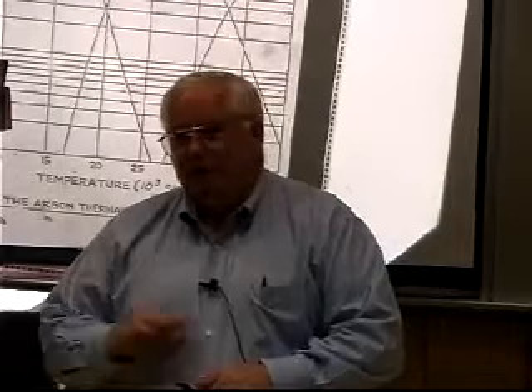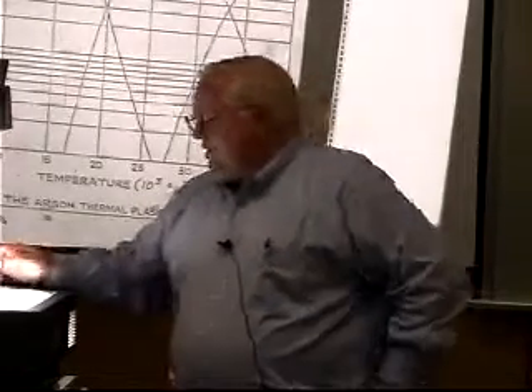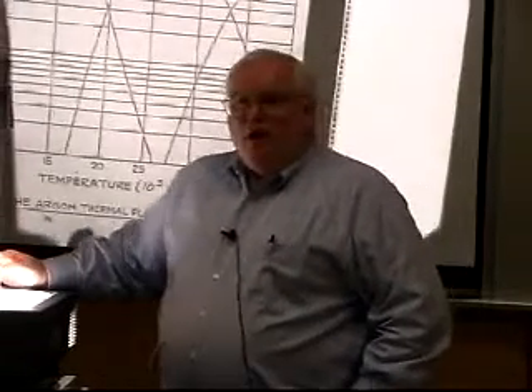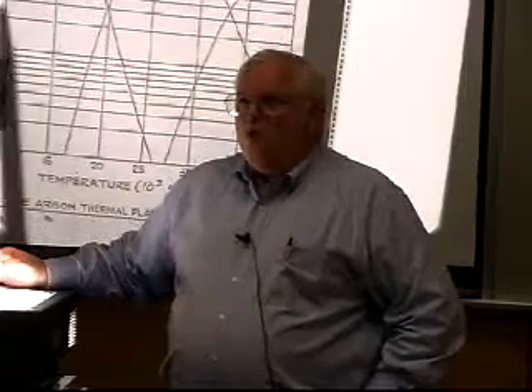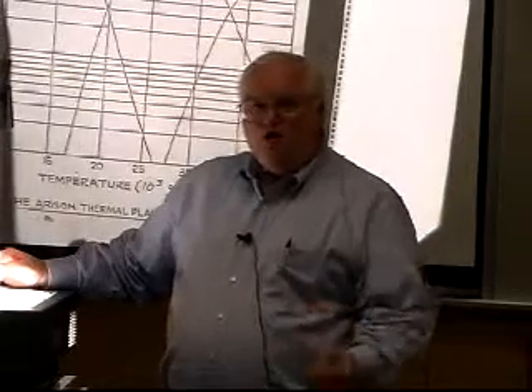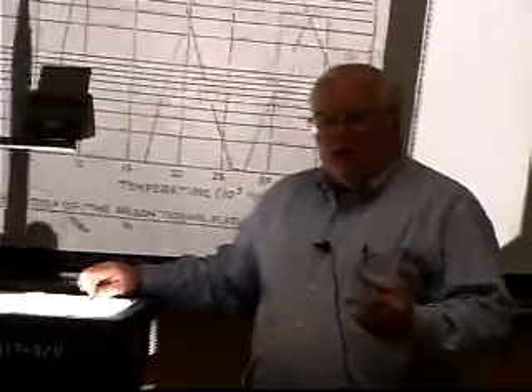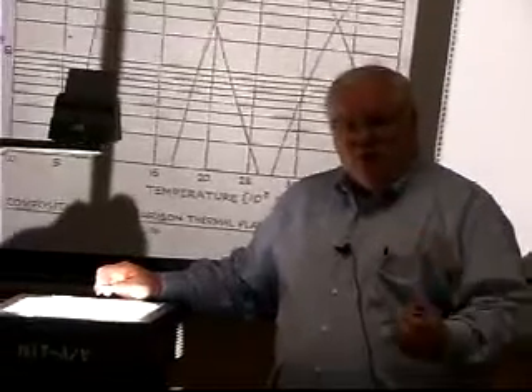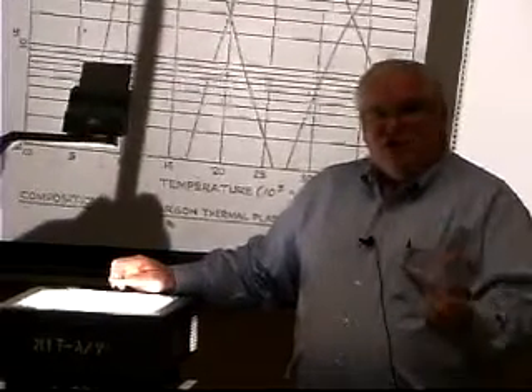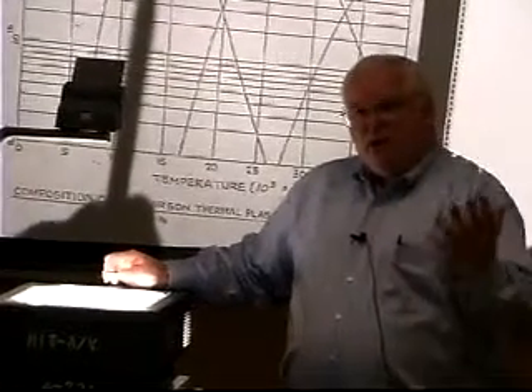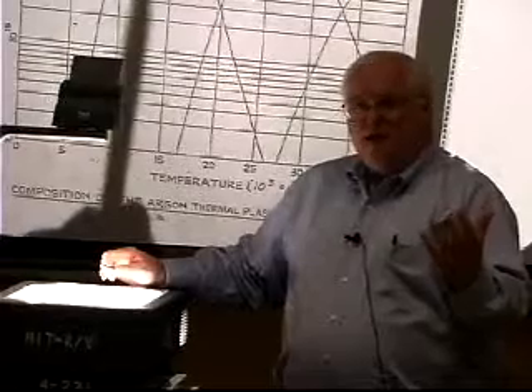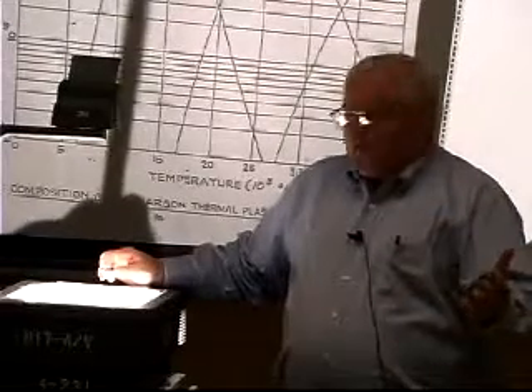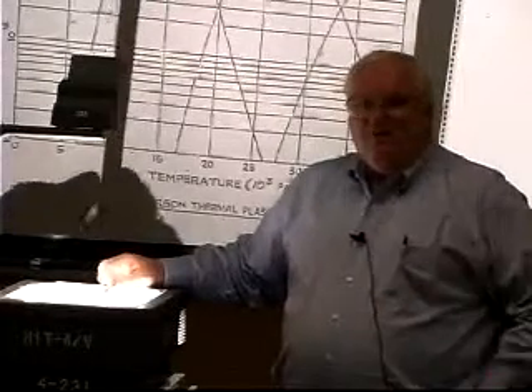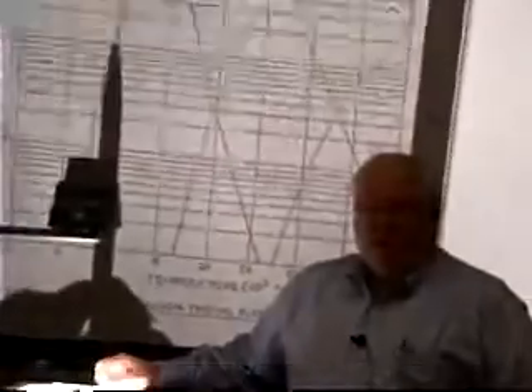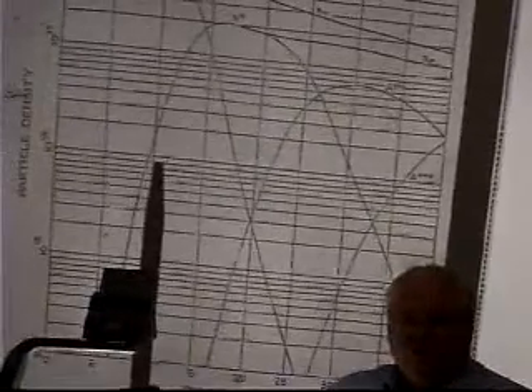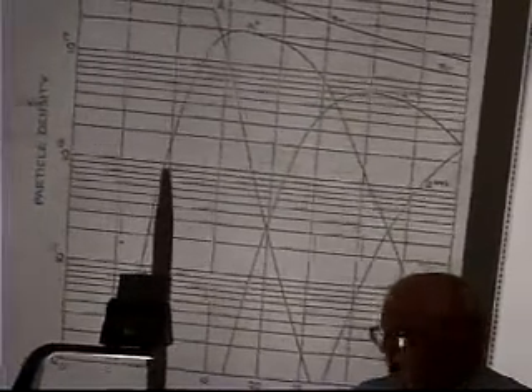And we'll go through that in a little bit, but basically what happens, I'm not welding with an argon arc. I'm not welding with a CO2 arc. I'm welding with a metal vapor arc. It turns out when I liquefy the pool, I'm getting sufficient energy to get 5 or 10% metal vapor up in that plasma. And in fact, that 5 or 10% metal vapor doesn't have a 14.6 volt ionization potential.